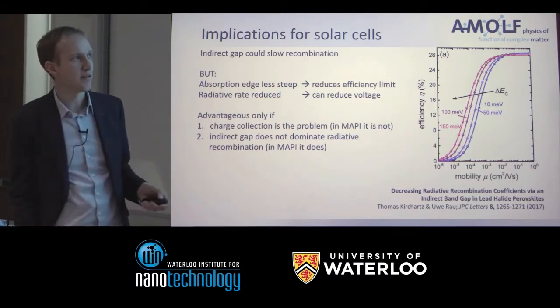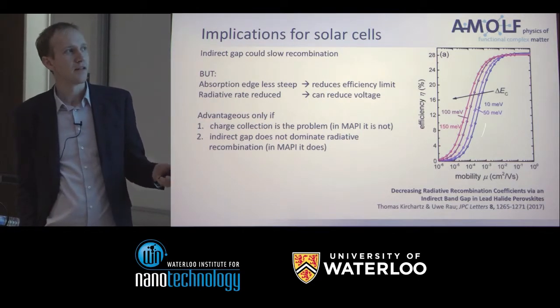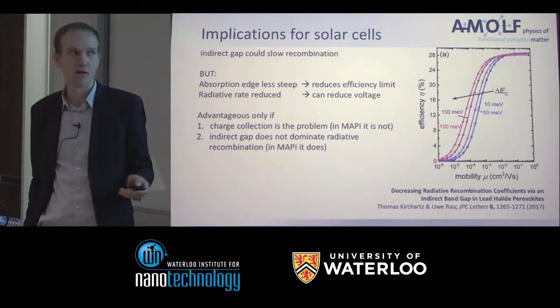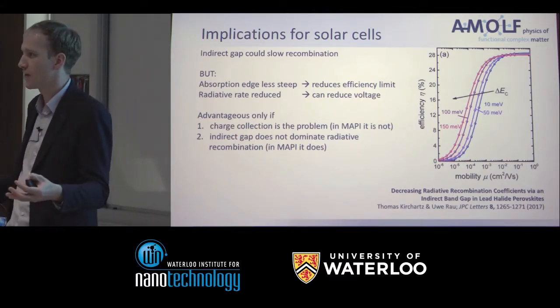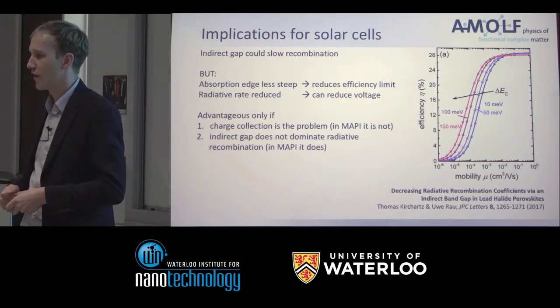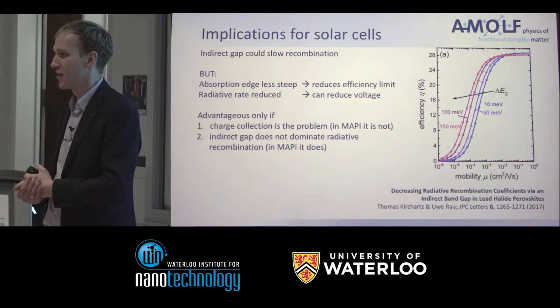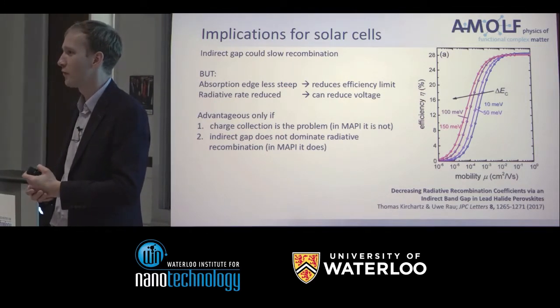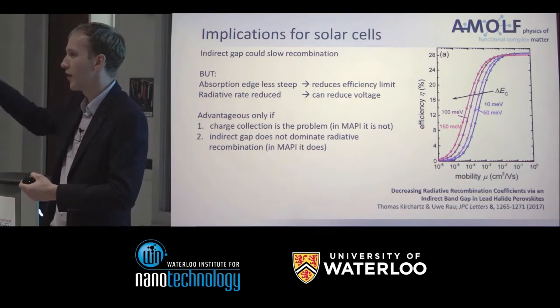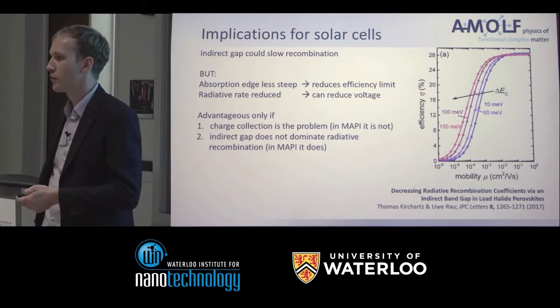And then the second question was, I think, was it that with polymer cells you are in this regime? That's what you said, right? Yeah. So if you have some process to stabilize the excited states, you would win. And I think that's true, if you would be able to find a state that lives longer without losing in mobility, right? Triplet states have much lower mobility, so there you wouldn't win. But if you have some state that's slightly lower in energy, still has the same high mobility as the high energy state and just lives longer, then I think you could actually make a more efficient polymer cell.